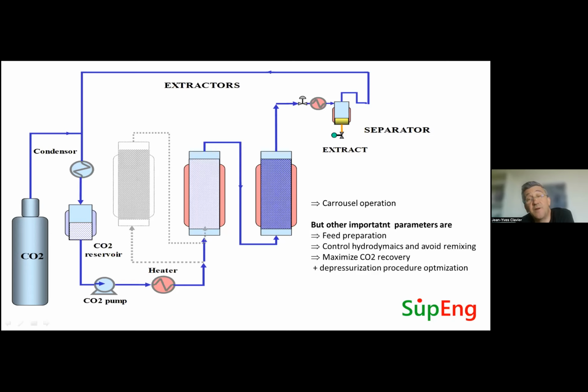And as it is a very large-scale application, like Judith said, we have to maximize CO2 recovery to minimize the impact of depressurizing the vessels. In these depressurization steps, we minimize the CO2 that remains in the vessel, and also optimize the depressurization of the vessels, because even if you depressurize correctly, CO2 has a great affinity for the plastic, and we have to adapt the depressurization procedure to minimize the amount of CO2 that remains in the plastic.